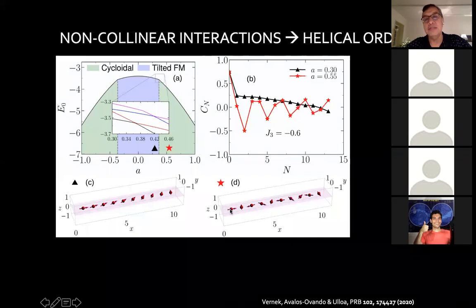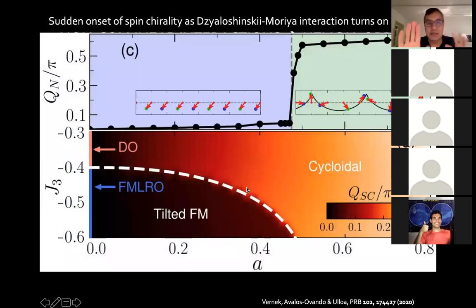Notice that here the spin is to the right, here is up, here is to the left, here is down, and so on. So I can see that there is a cycloid that is developing in this case, only because I've increased the Dzyaloshinskii-Moriya. Here is the correlation function that quantifies this effect. You can see that in the strong Dzyaloshinskii-Moriya case you have this oscillatory pattern, while in the other case it's kind of monotonous because it's ferromagnetic. So interestingly, you can actually map the entire phase space for various values of the Dzyaloshinskii-Moriya